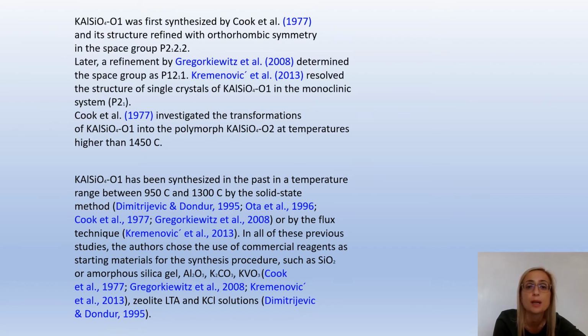KAlSiO4-O1 was first synthesized by Cook et al., who refined its structure with orthorhombic symmetry. Later, Kremenovich resolved the structure of single crystal of KAlSiO4-O1 in the monoclinic system. Cook et al. in 1977 investigated the transformation of KAlSiO4-O1 into the polymorph KAlSiO4-O2 at temperatures higher than 1450 degrees Celsius. The mineral has been synthesized in the past in a temperature range between 950 degrees Celsius and 1300 degrees Celsius by the solid-state method or by the flux technique.